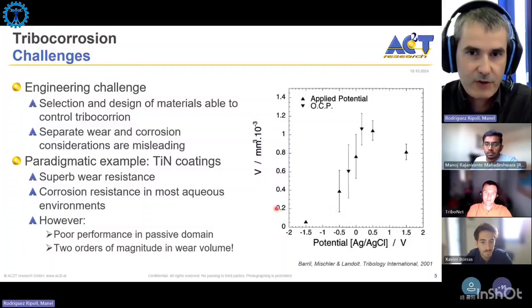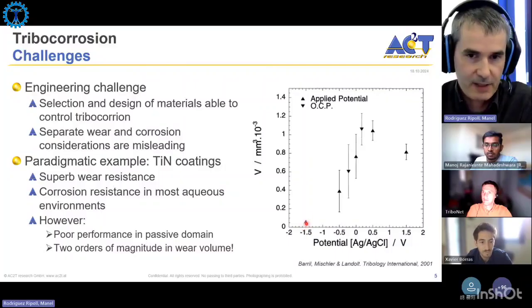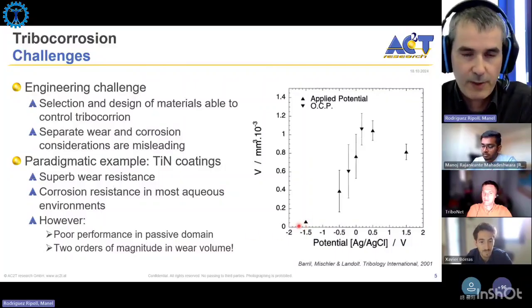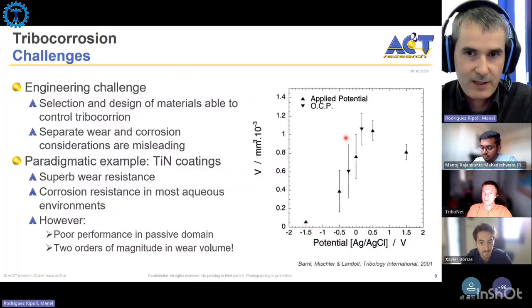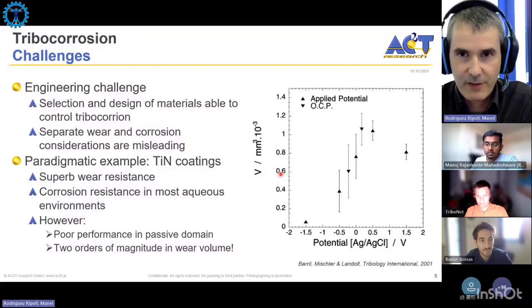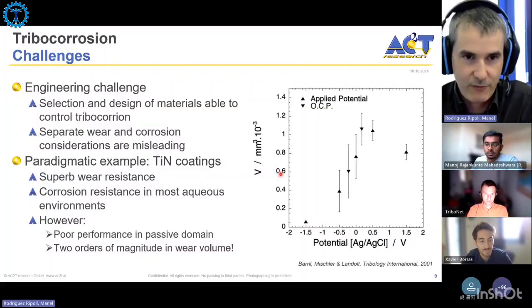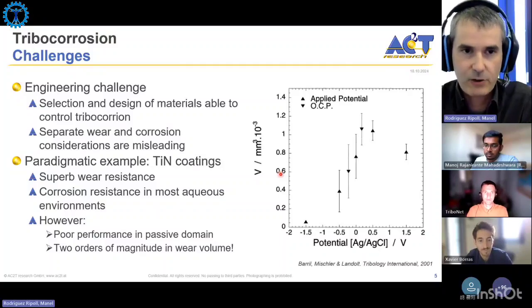And you can see, for example, in this graph the removed wear volume as a function of the electrode potential. For example, if you have cathodic potential, where mostly corrosion is inhibited, we have very low wear, which will be close to the pure mechanical wear. And when we apply an anodic potential, the tribocorrosion wear can be up to 2 orders of magnitude larger. So it means that we need to use tribocorrosion methods to evaluate materials that are suitable for tribocorrosion applications. So the separate consideration of wear and corrosion will be very often misleading.